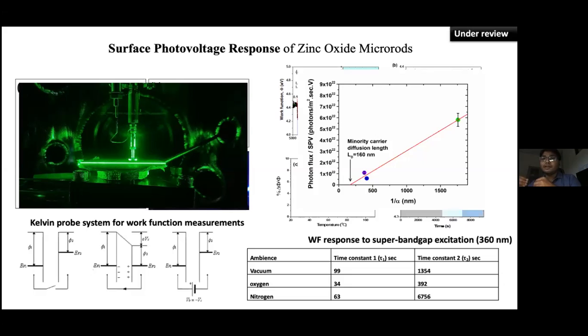So what we do is, we look at the response in the work function with different wavelengths, and parallelly from the UV visible spectrum we have already quantified the absorbance alpha value for a given wavelength. So the surface photovoltage, that is the change in the work function for a given photon flux, normalized by intensity and by area, is plotted as a function of the alpha value for a given wavelength. For example, this is for 530 nanometer, this is for 360, and this is 320. When you have such a graph, you can draw a line and see where it intersects the x-axis. The x-axis intercept gives you the diffusion length of these minority charge carriers.